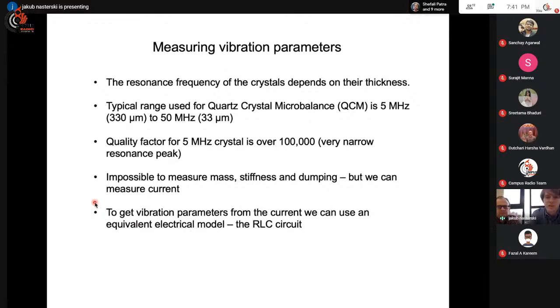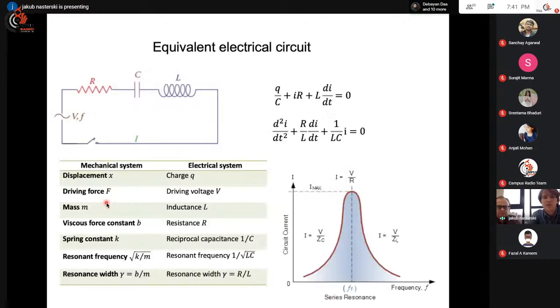So remember what I showed you a few slides ago, that when we oscillate this crystal with alternating current, as the oscillations of the crystal increase, the current drawn by the electrodes also increases. So the current will be proportional to the displacement of the quartz. And this is just the equivalent electronic circuit. We have the resistance, the capacitance, the inductance, and you can compare them to stiffness, to damping, and to mass. And if you look at the equation for this, it's the same form as the mechanical equation we've seen earlier.